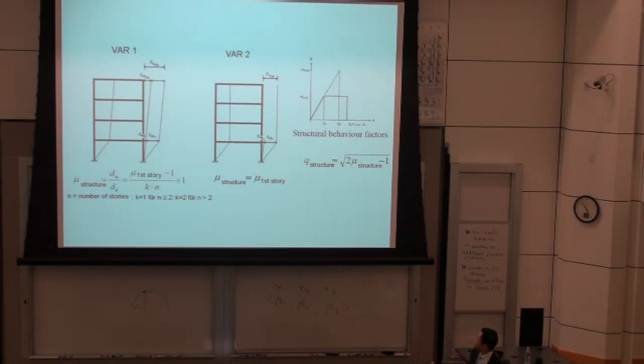And the second boundary condition, the extreme alternative, is where you have again the elastic displacement at the bottom plus the plastic displacement, then it goes parallel up. Both alternatives, left and right, are not realistic. Somewhere in the middle is the reality. But it is just to have an approximation. And finally, you can define very easily with the well-known equation the R values or q values, behavior factors, response factors, however some codes call it, as the square root of 2 times mu structure minus 1. This is assuming